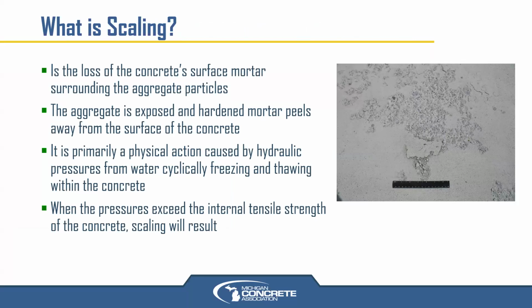This is the loss of the surface mortar on top of the concrete slab surrounding the aggregate particles, essentially. The aggregate gets exposed, the mortar's peeled off. It's a physical action caused by weak paste on the surface, but it typically happens through the first or second or third winter, whenever we have a harsher winter. A lot of different factors go into that, but water can soak into that weak porous paste that did not get cured properly and had high evaporation rates right after it was placed.